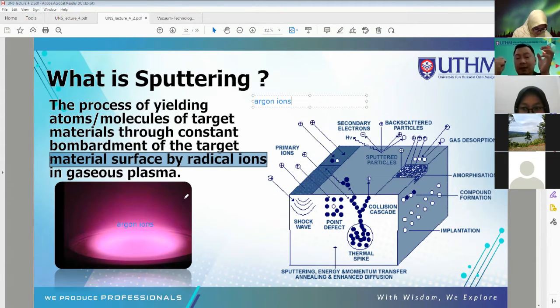So we have an argon ion, a very energetic one because it is an ion. We supply a negative voltage to the target, and then the ion will hit the target, and by hitting the target we release atoms from the target. This is called the process of sputtering. We can see the ion hit the target. So what will happen when it hits the target? It will release a secondary electron, do gas desorption, and do ion implantation. These are the phenomena that will occur when the argon hits the target.